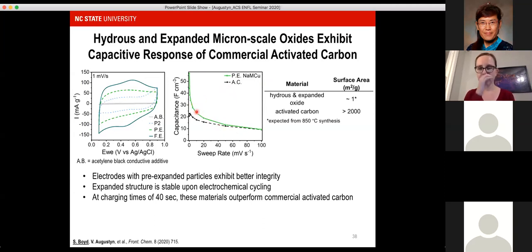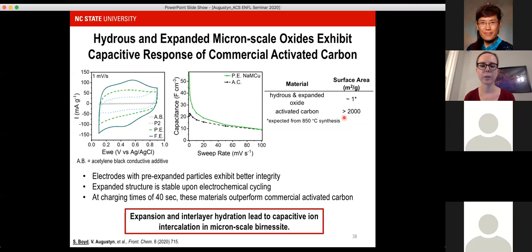And the surprising thing is that we're taking a material that has a surface area of about 1 meter squared per gram, which is what we expect from the high temperature synthesis, and comparing it to activated carbon that's synthesized with a surface area of over 2,000 meters squared per gram. So we think that the expansion and interlayer hydration is what leads to the capacitive ion intercalation in now this micron scale birnessite material. So you don't have to actually exfoliate the material completely to access a high surface area response, because now you have this confined and hydrated interlayer.